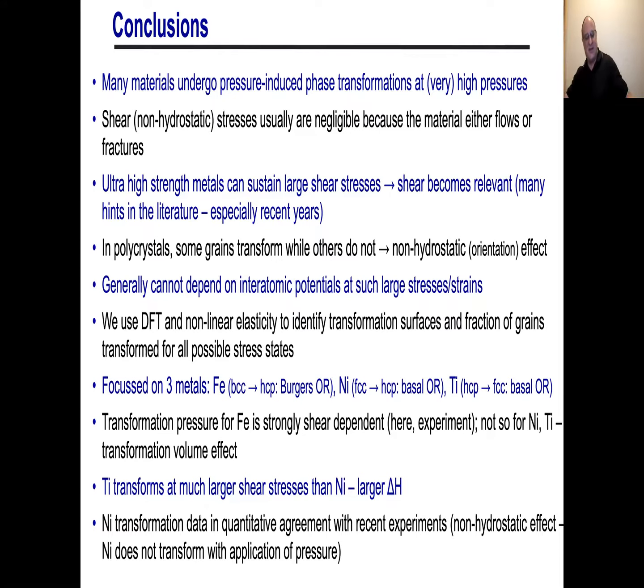The other thing I would suffer from if I did that is, if it's diffusional, I don't necessarily have as strong an orientation relationship. So if I have one grain here, it's going to transform to another one. That means I have to look at all possible orientations. It means I have to do a search over all of SO3 in the alpha phase, and then for each one of those do a search over SO3 in the other one. And that's a 6-dimensional calculation at each point in stress space. So the bottom line is, it's ugly. It's a good question, but I'm afraid of it. Okay, thank you.